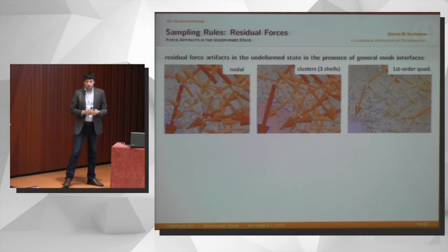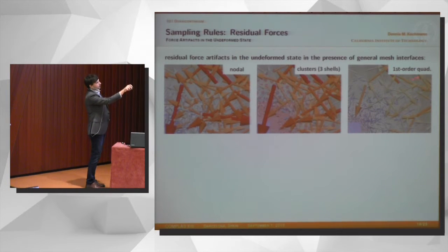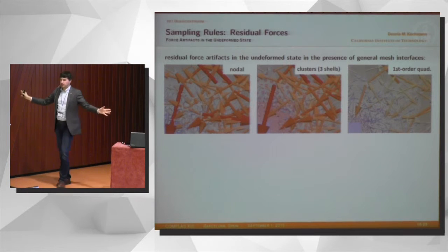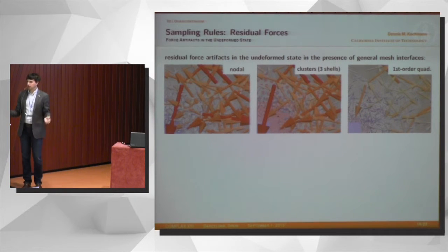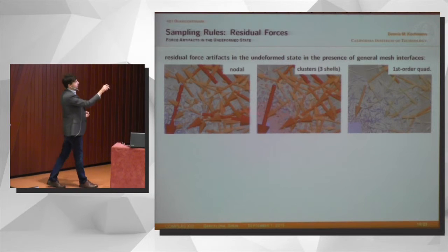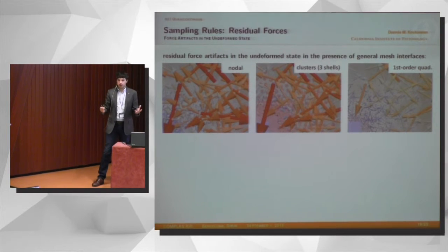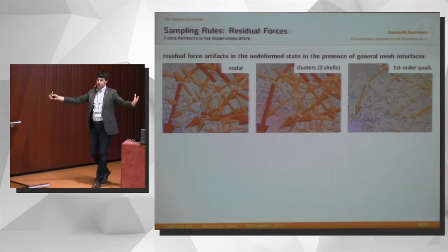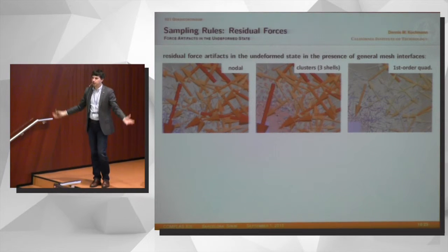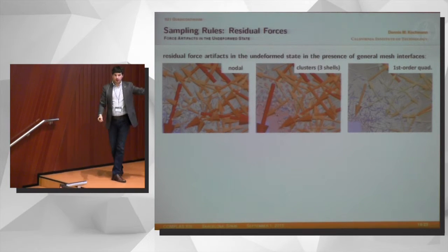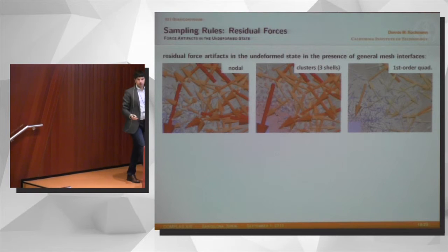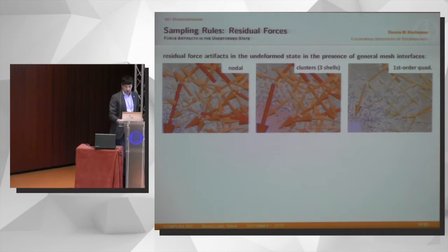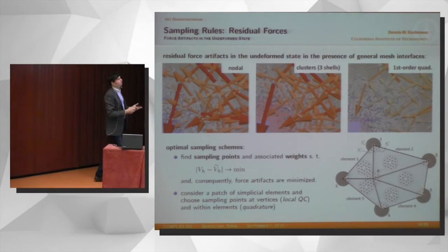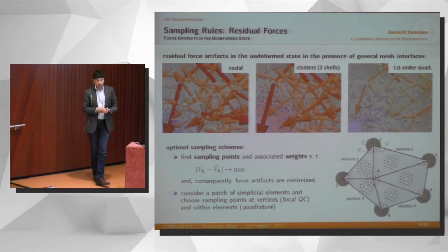Just to give you one example, this is a scenario where I have full atomistic resolution in the bottom left corner, and I coarsen away. This is a perfect single crystal where I would not see a single force in the undeformed configuration. And what you're seeing here are the forces which I computed in the undeformed configuration when I used this coarsening. So these forces just pop up. They're non-physical, and if you were to equilibrate that, you get anything but a realistic physical solution. It's just nonsense.